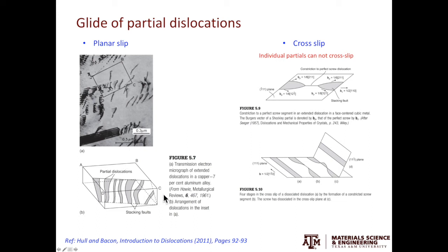One interesting thing to discuss here is how partial dislocations move on the slip planes. If you have a metal having low stacking fault energy, the dislocations will dissociate and form two partials. In most of the cases, you will see prominent planar slip. That means most of the slip are confined on a single slip plane, as shown in the example on the left. Cross slip, that is to slip from one 111 plane to another 111 plane is possible but very difficult.